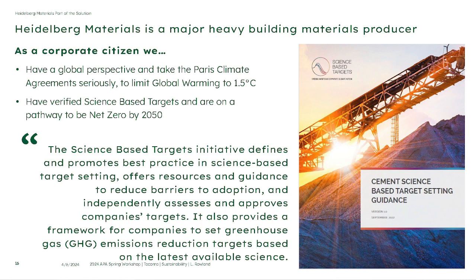The other thing we're going to do is we're embracing carbon capture, utilization, and storage. I'll tell you about that in a little bit more detail, but essentially what that is doing is we're capturing that CO2 that we release from burning our fuels and calcining our limestone out of the stack. And instead of letting it go out into the atmosphere, we're capturing it, we're compressing it, and we're pumping it down in the ground for permanent storage.